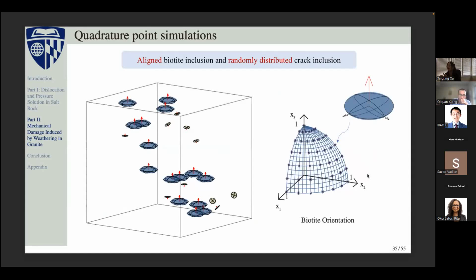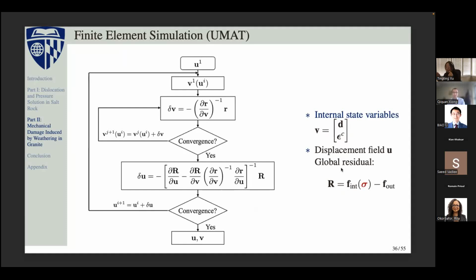So here is a sketch of this material point study. You can see that we consider randomly distributed crack inclusions, and we consider aligned biotite inclusions to investigate the influence of the different biotite orientations. So that is the study conducted in the material point simulation. With this simulation, we are trying to implement it into one of the finite element solvers, which is Abaqus, and we use a user-defined material subroutine to do that.